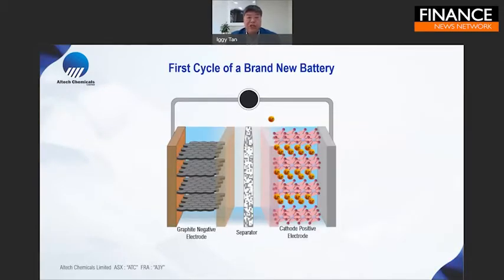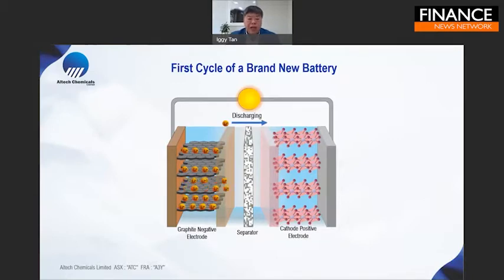Just a bit of education on lithium-ion batteries. You've got a cathode on the right-hand side. You've got an anode on the left-hand side. As you charge the batteries, the lithium ions move from the cathode to the anode. And when you discharge a battery, the lithium ions move back. What a lot of people don't realize is that 10% of the lithium actually stays on the anode side and becomes inactive to the battery. This is called the first cycle lithium loss capacity. So imagine 10% of the lithium becomes inactive before the customer even gets the battery.